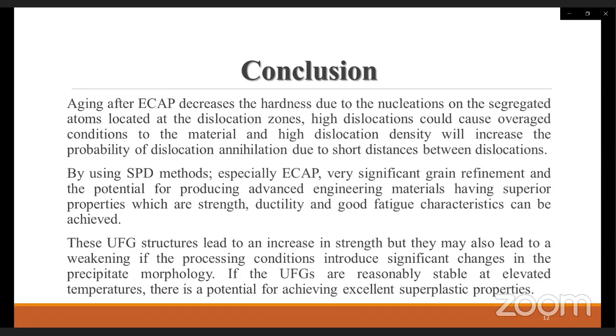By using SPD methods, especially ECAP, very significant grain refinement and the potential for producing advanced engineering materials having superior properties, which are strength, ductility, and good fatigue characteristics, can be achieved. And these UFG structures lead to an increase in strength, but they may also lead to a weakening if the processing conditions introduce significant changes in the precipitate morphology. If the UFGs are reasonably stable at elevated temperatures, there's a potential for achieving excellent superplastic properties.